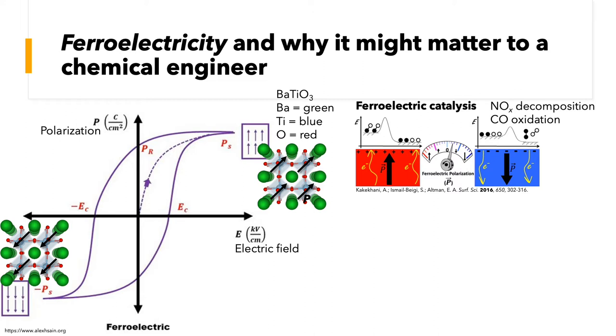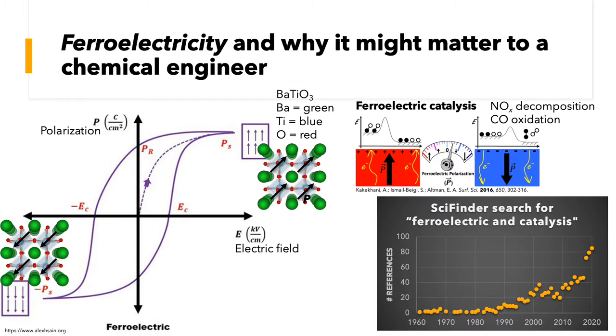But why might this matter to a chemical engineer? Well there's probably many reasons. Recently there's been a resurgence of interest in ferroelectric catalysis, where the change in surface charge associated with up and down polarization of a ferroelectric is used to drive chemical reactions like NOx decomposition and CO oxidation. This has become a hot topic of late with over 200 publications in the last three years, but there remains a need to understand and develop strategies for tuning the catalytically relevant ferroelectric properties, like P sub s, which determines the amount of surface charge, and E sub c, which determines how easy it is to flip the polarization, an intrinsically nanoscale process.